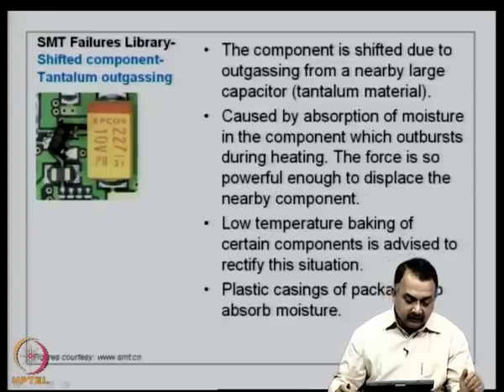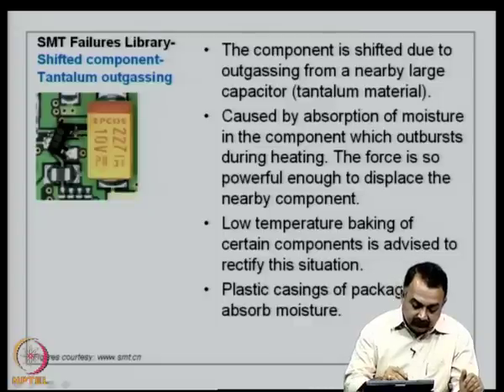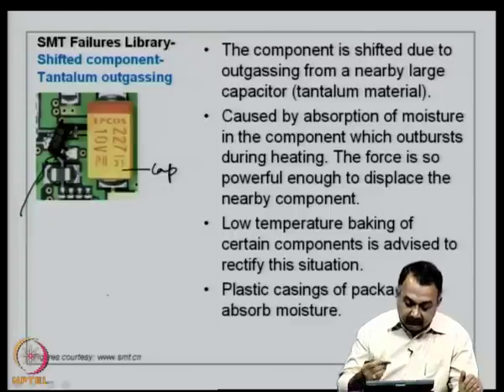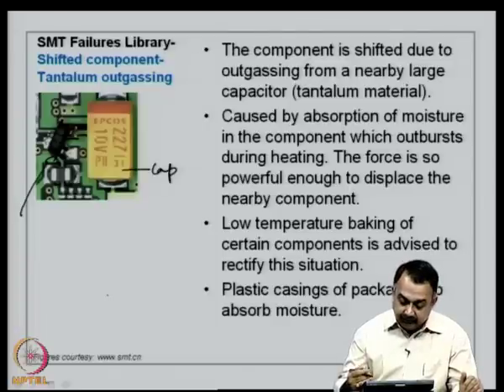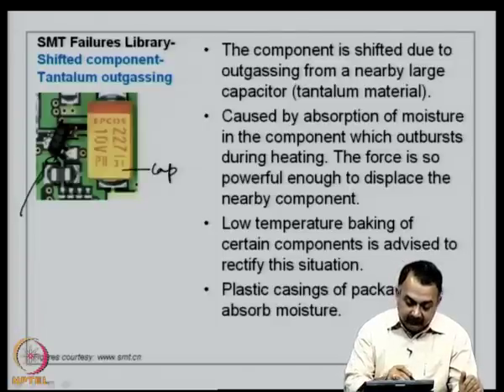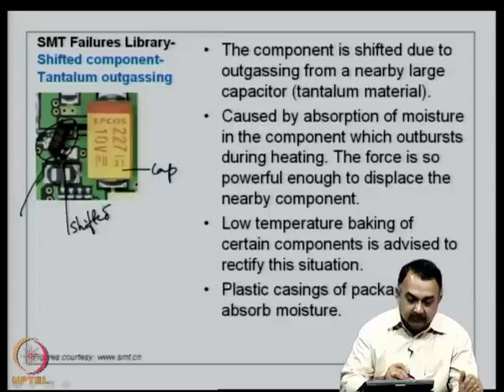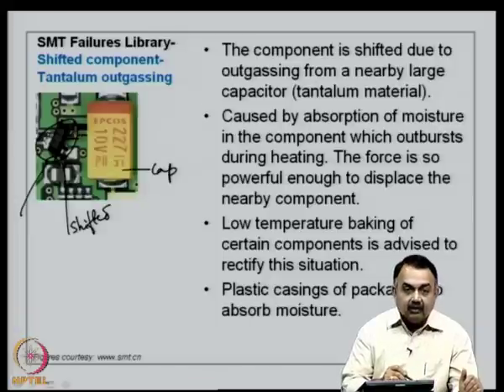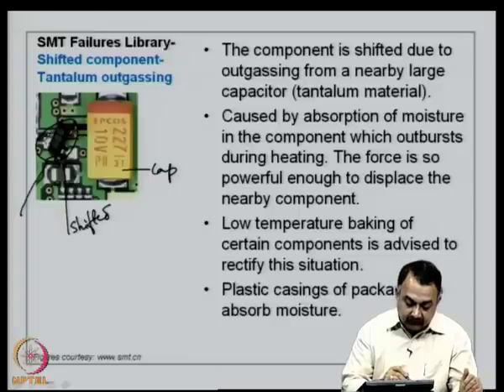Now, the other failure is a shifted component and tantalum outgassing. Here you can see there is a large tantalum capacitor, and here you can see a small component. Now, the solder paste has been dispensed and reflow has been initiated. During the reflow process, the component you see here has been shifted from its footprint due to outgassing of gases from this particular large tantalum capacitor.